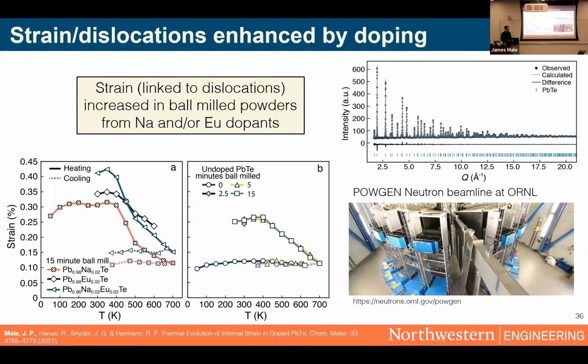So this strain is indicative of high dislocation densities being in that sample, which is kind of what we would expect from this plastic deformation of ball milling. We also noticed that if we added sodium or europium or a combination, that strain essentially can exceed its sort of equilibrium concentration. So clearly the presence of these point defects is causing more dislocations to be frozen in the lattice and increasing our overall strain.